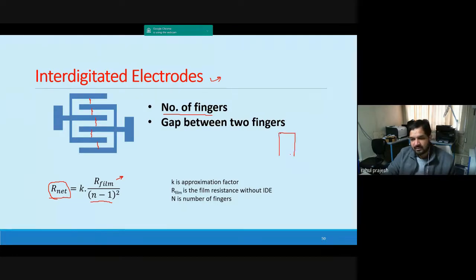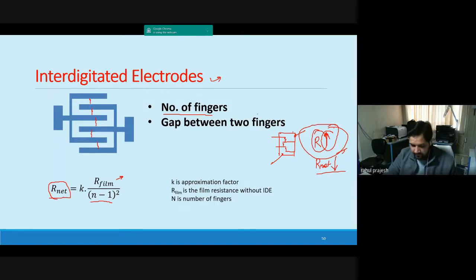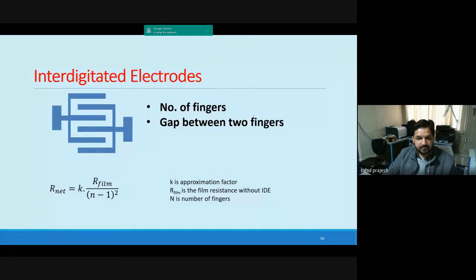For example, you have some material and you want to measure its resistance using two probes. You will have some resistance, and this resistance will be very high. For semiconductors, the resistance is very high. But if you make interdigital electrodes, what happens? These electrodes have resistance in parallel, and because of the parallel combination, the net resistance will be very low compared to the initial resistance, which makes it easier to measure. In this particular case, it is difficult to measure. That's why I use interdigital electrodes. And there are other advantages of interdigital electrodes that you can read about and discuss with me also.